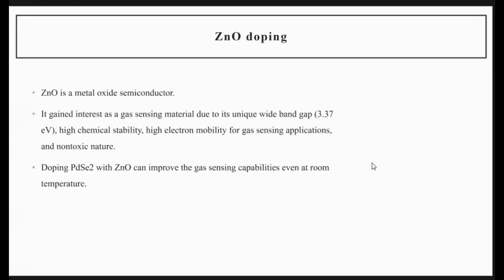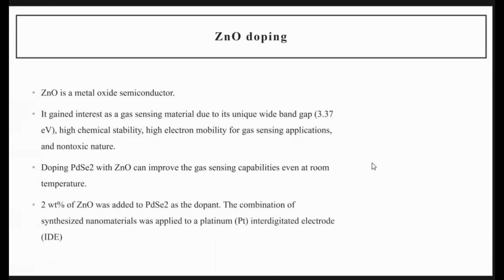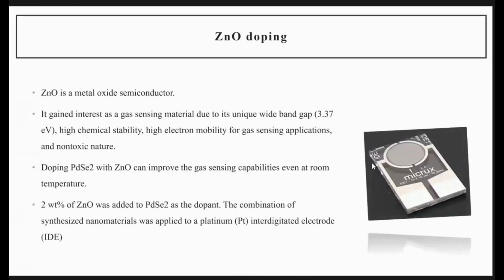Zinc oxide is a very good metal oxide semiconductor for hydrogen sensing. It is also sensitive to light. So we thought of incorporating these two by adding 2% of zinc oxide to the palladium selenide for detecting these reducing gases. So we took 2% of zinc oxide with the palladium selenide, and we dispensed it over the platinum IDE.